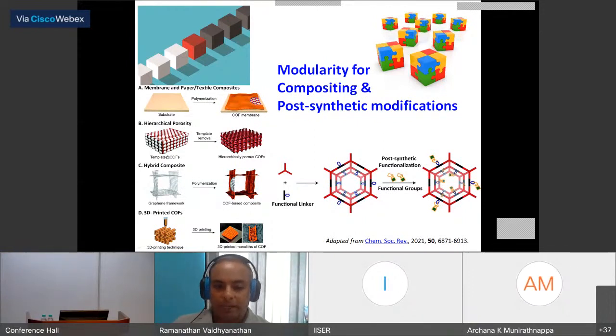Same way, you can develop hierarchical porosity. You can combine it with very conductive materials like graphene using this modularity, so that you make the modules compatible with graphene. Then you can make composites. And very recently, even 3D printing inks have been developed by the modular nature of the COF, so that it is becoming very highly dispersive in a very thick gelish solvent. And that makes it very suited for 3D printing.